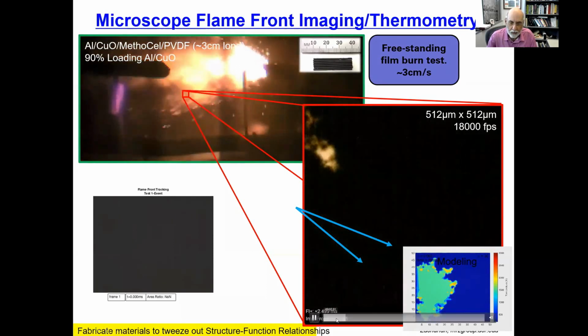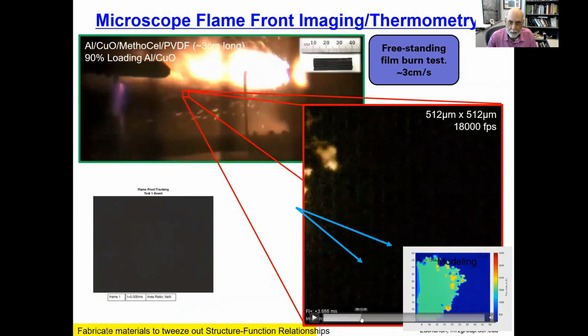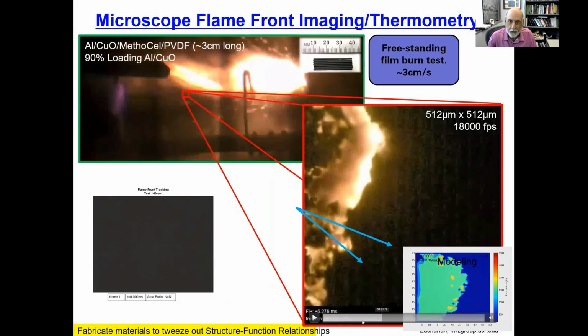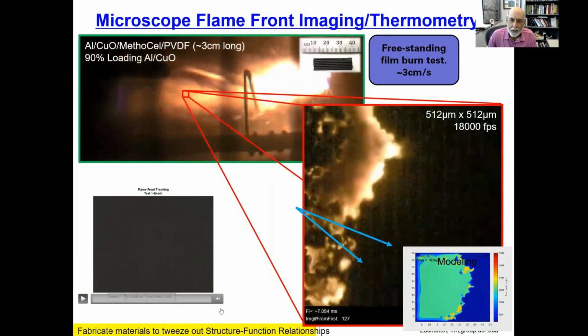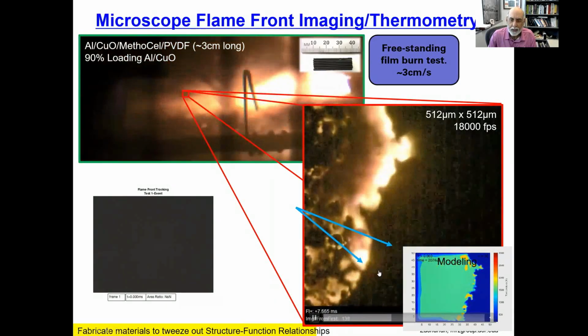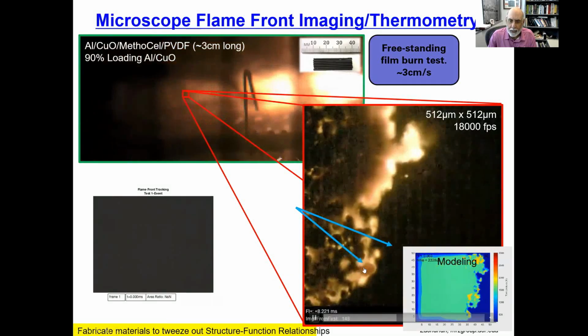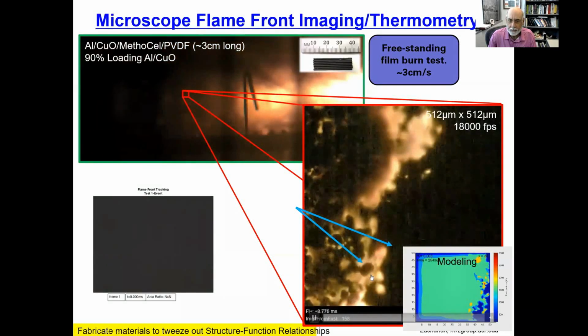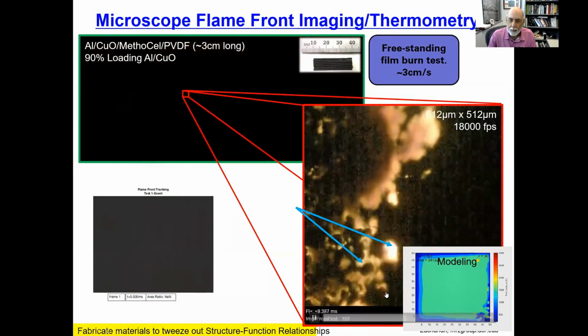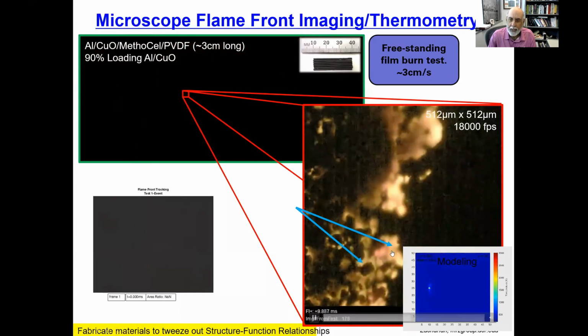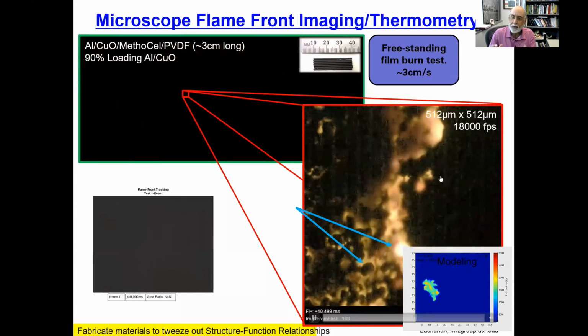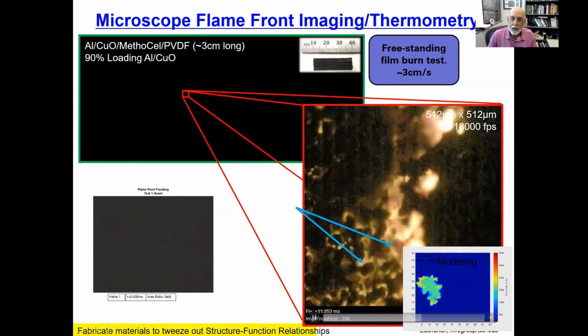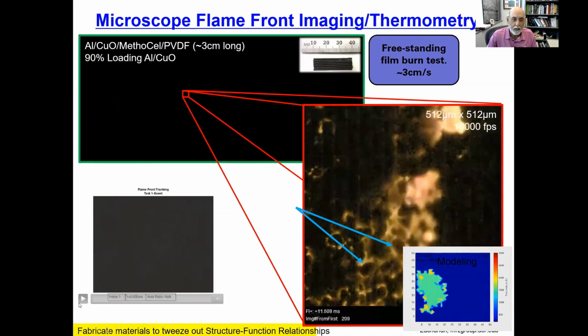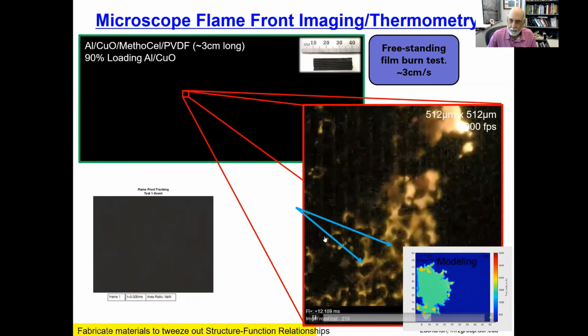It's a little bit slower. Try and speed it up a little bit. Here we go. And you can see now the reaction front is hopping and leaving behind large particles. Remember, we're starting with nanoparticles, but we're leaving behind large particles. Those are the sintered particles that were occurring on this system.